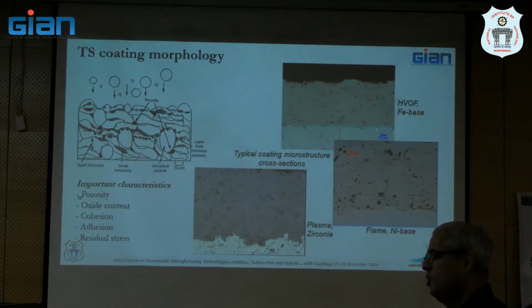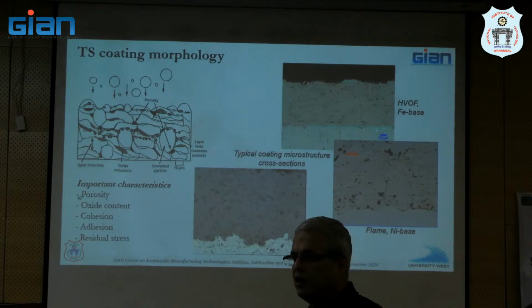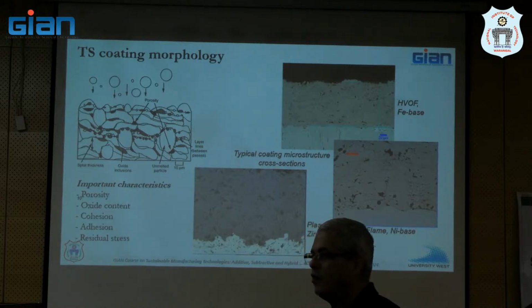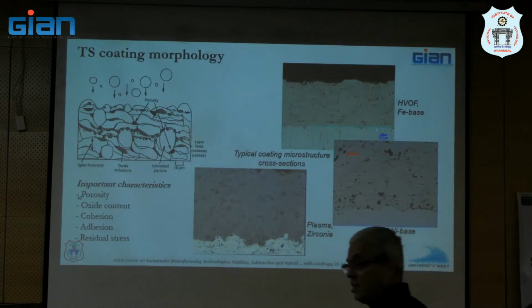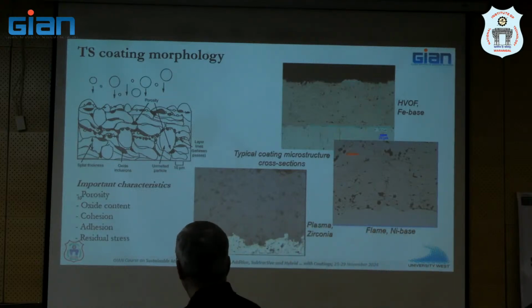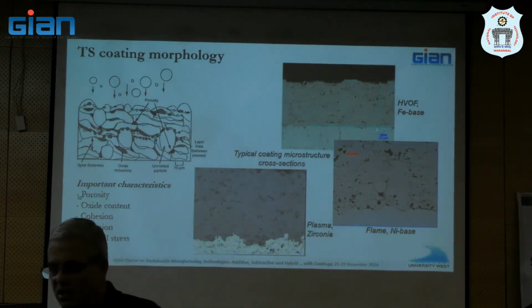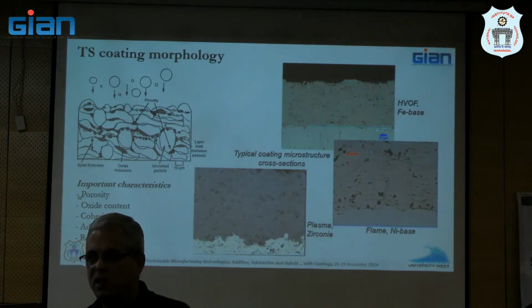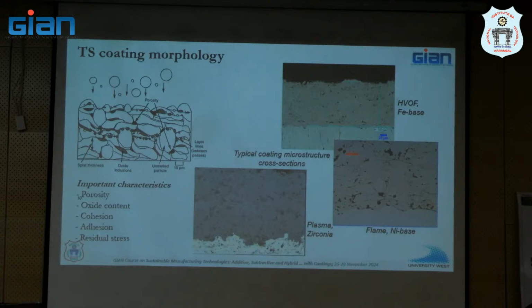Imagine a thermal barrier coating which was fully dense, no porosity, no nothing. Would it survive? No, it will not survive because of thermal stresses, right? There is no way to accommodate thermal stresses if it's fully dense, correct? Here the bonding will be good, but if there is no porosity, there is no way to accommodate thermal stresses. Imagine that you are a coating in an aircraft, and the aircraft is taking off and landing. So what does it do? It's basically heating up and cooling, and that induces thermal stresses. How will the coating accommodate stresses if there is no porosity, right? Then it will immediately fail because of the stresses.